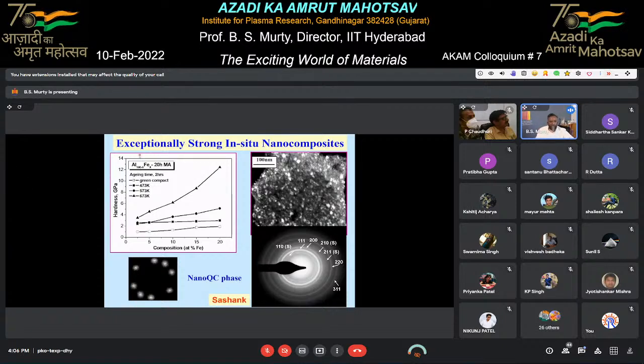Here is an aluminum alloy where the hardness can go to 12 gigapascal, 12,000 megapascal, which means a yield strength of 5,000 megapascal, which means 5 gigapascal. 5 gigapascal yield strength is like a dream for any metallurgist, for an aluminum alloy. That means it is much stronger than steel in terms of what is called specific strength. When you take strength divided by the density, you will know that this material, for a very light weight, gives you very high strength. And this is possible.